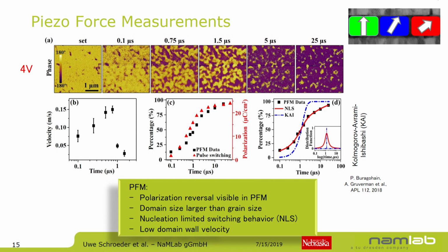PFM, as you heard in the beginning, there are lots of people doing PFM. PFM was very critical in the beginning, and still you have to make sure that you measure the right properties of the hafnium oxide, since from Oak Ridge, we've seen results where even amorphous hafnium oxide shows a nice hysteresis loop. But if you make sure that you have the right measurement procedure, you can also be sure that you find the ferroelectric properties are not just charging of the interfacial layers.